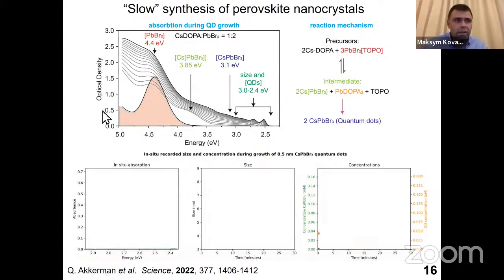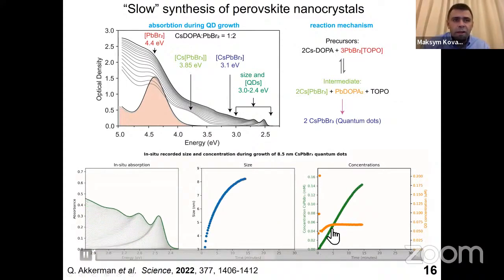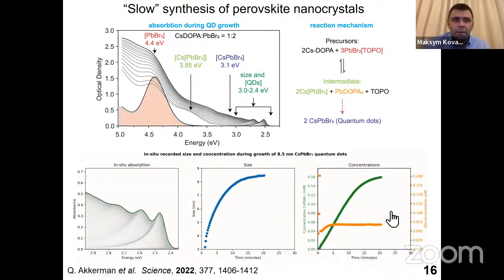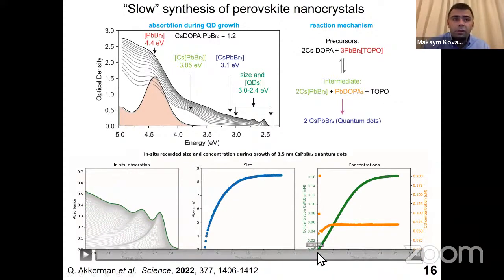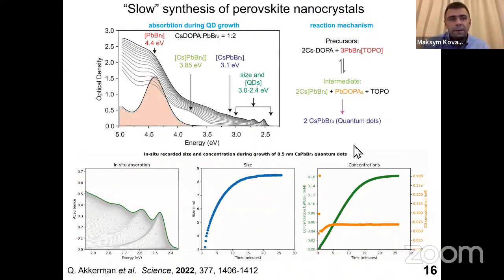And just to give you an idea, you can actually observe that your nanocrystal quantity, the concentration of quantum dots, will rise and then saturate. That means you have reached the plateau in your concentration and in your size. You know then that at this moment the whole reaction is finished, and then you can isolate your nanocrystals in a high yield. So just to give you an idea,